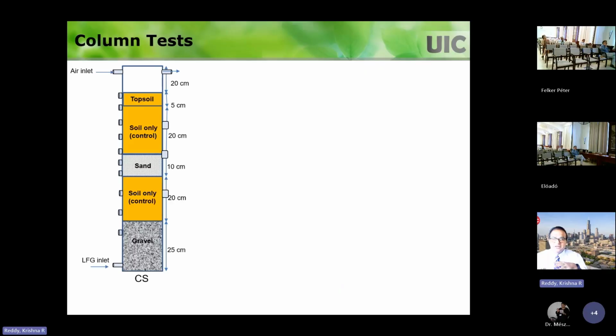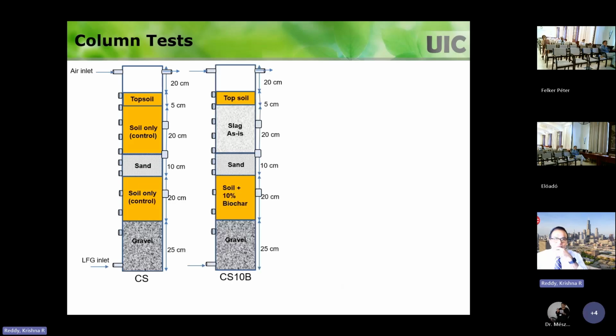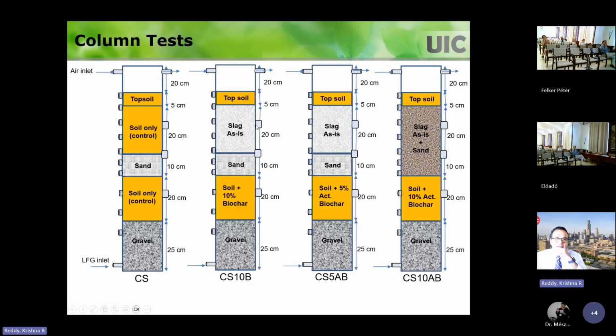Now, in the biogeochemical cover system that we are proposing, we want to have both of them, right? So we try to test it. So basically, this is the soil-only layer. This has the 10% biochar at the bottom, and then you have a slag on the top, right? So this small sand layer, we put in because we can measure the concentration that is coming into this. So we can see how much is coming from the biochar amended soil layer, and then how much is feeding into the slag layer, and we can measure what is coming out. So the sand layer is not necessary, but we just did that one for measuring the concentrations. But the whole idea is this is only soil.